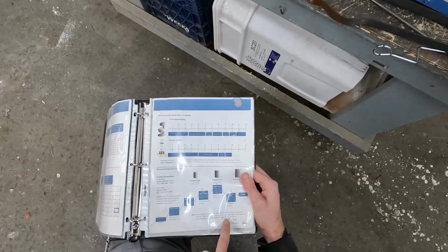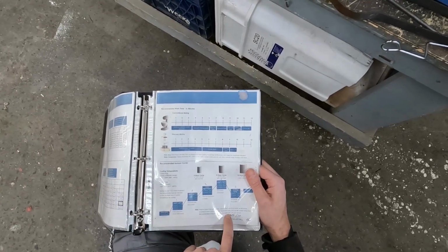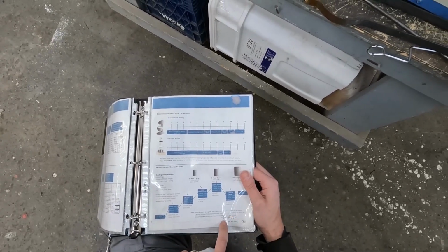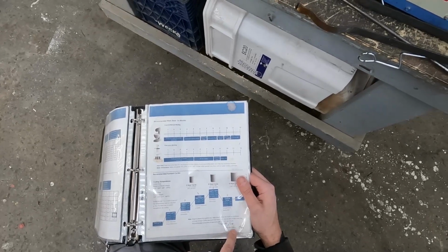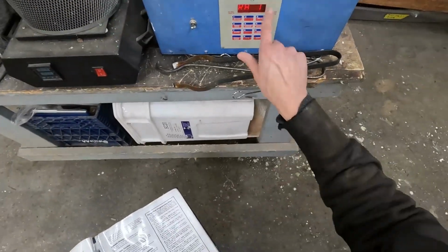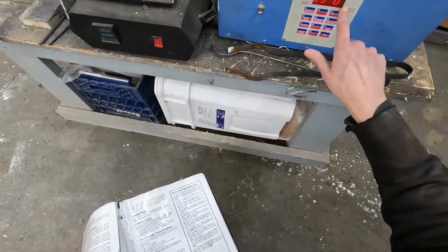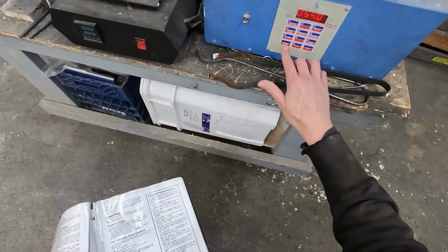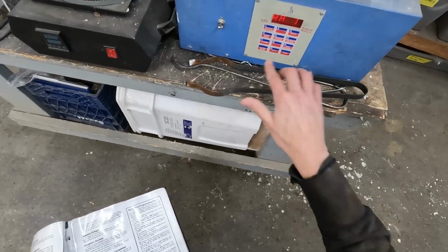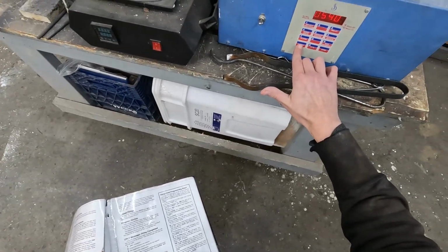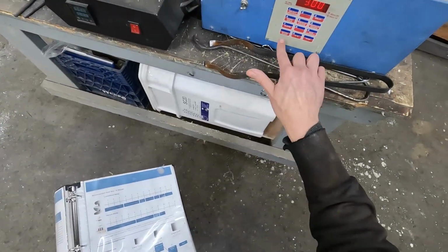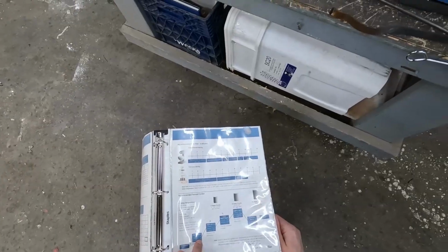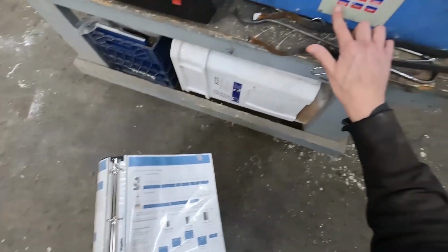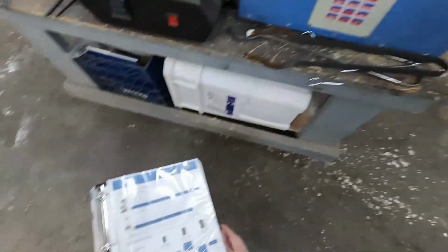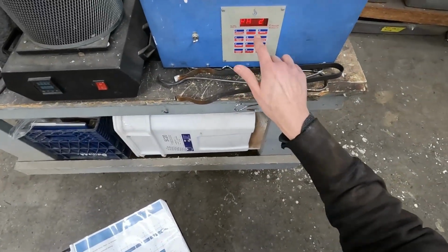There's a little note here that the ideal rate is 9 Fahrenheit per minute, which is 540 Fahrenheit per hour. Okay, so that's already in here. Sometimes the same ramp program will be in here from a previous burnout. And so we just kind of go through and make sure the settings are correct. So ramp 1 is going to go up at 540 Fahrenheit per hour. Target temperature of the first one is 300, that's correct, so hit enter. For the 8-hour cycle, we hold it for 1 hour. So we hit enter. Now we're going to ramp 2. Ramp 2 is also going to go up at 540.